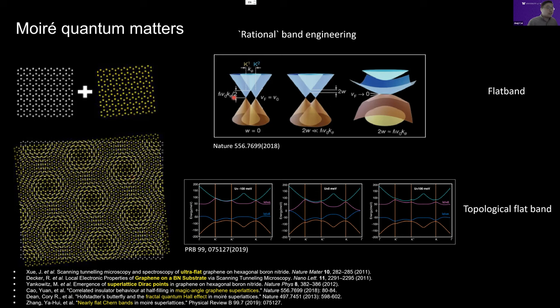What I've shown here is that if you have two sheets of graphene, which is a Dirac semimetal, you can put them together. The tunneling effect between these two twisted layers actually gives rise to those flat bands. And further theoretical study proves that in twisted double bilayer graphene, as an example, an electric field can tune the topological property of this flat band, and you actually end up with a topological flat band.